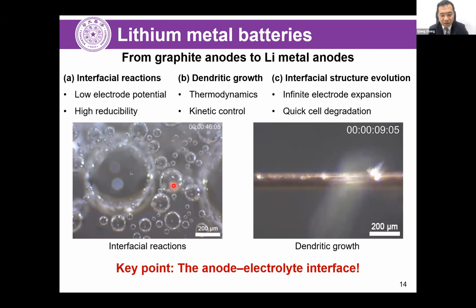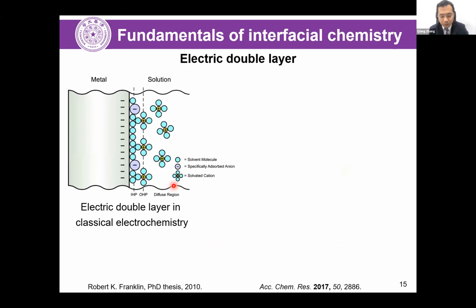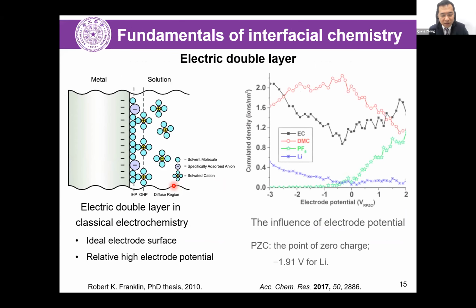So we try to focus on the interface and try to probe what's happening here. In fact, if you try to draw this metal anode surface, there is always some chemical adsorption on the surface. Inside, we call this the inner Helmholtz plane, in which some ions prefer to adsorb on the surface. While in the outer Helmholtz plane, there are some ions, and also there is a long diffusion region in which the ions will diffuse from the main phase to the interface. So in this case, what happens at the interface and how can we regulate the interfacial reaction?